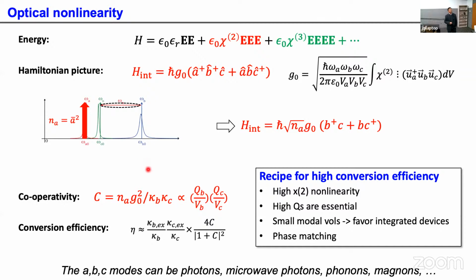Often we want this cooperativity to be one to have a unitary microwave to optical conversion or optical to optical conversion. But in real device implementation, you have other factors because we're using a cavity, and the cavity coupling condition also comes into play here. There's a prefactor. If you have a fully overcoupled system, like a superconducting resonator, you are often overcoupled by a factor of 100, so this number is almost 1. But in the optical domain, that's always a compromise, so you normally don't have a high overcoupling ratio. So those are the requirements.